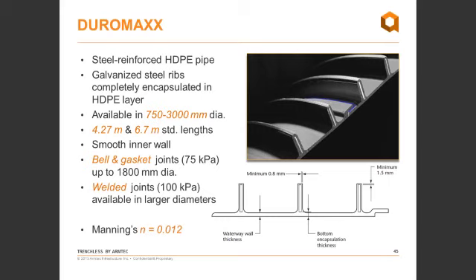And the key feature of this pipe is that it has the inner wall, which is fully HDPE, but it has steel ribs that are wound helically along with it. These are galvanized steel ribs. It's a high-strength steel, and it's completely encapsulated in HDPE. So it prevents the steel from access to the environment. The steel is not exposed to water or oxygen, no chance to corrode. So we really consider this an HDPE pipe in terms of durability.